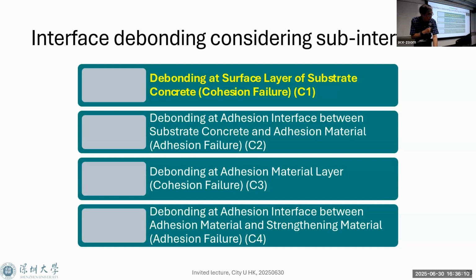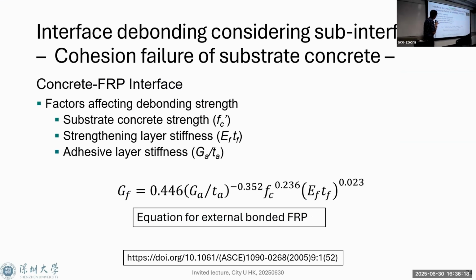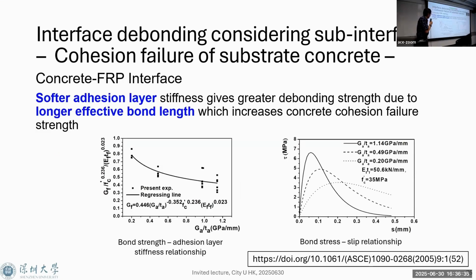So this one, debonding at the surface layer of the substrate concrete, we call C1. This is an early contribution of Professor Dai Jianguo. He proposed this formula in his PhD study, in fact. Based on his study, better debonding strength comes from a softer adhesion layer. A softer adhesion layer in the bond stress-slip relationship shows a much higher peak bond stress. But this is only true for the substrate concrete debonding case.